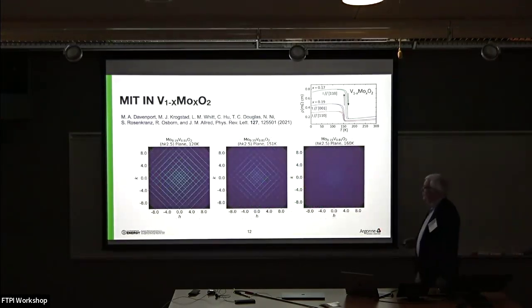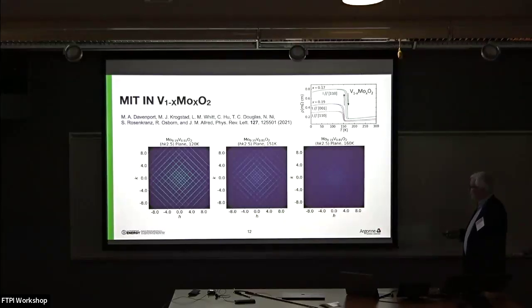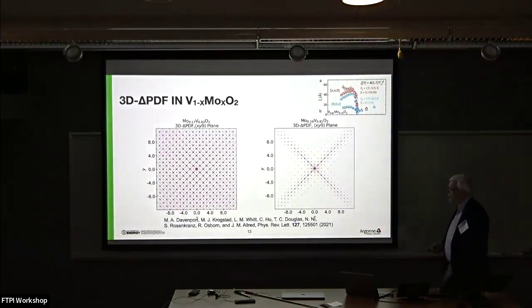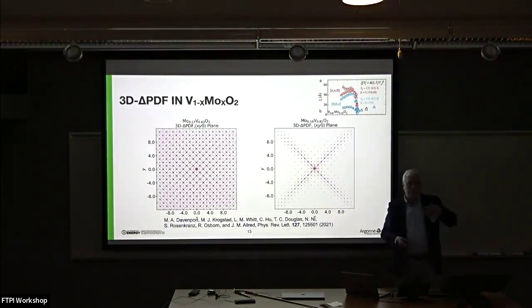And indeed, the rods become something like an order parameter. They're very weak above the transition, and much stronger below the transition. You can actually track them that way. What's going on? If you convert it to 3D-ΔPDF, you can see immediately what's going on. You can see the origin of those rods.